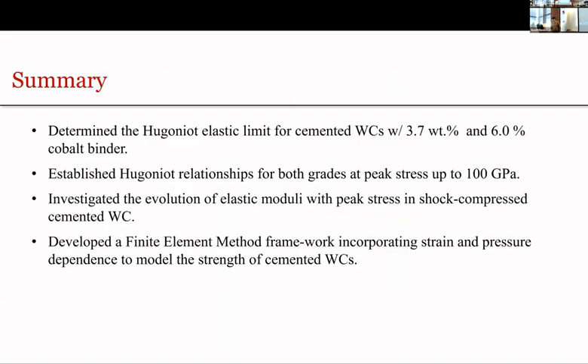So in summary, we have successfully determined the Hugoniot elastic limit for both grades and established the Hugoniot relationship for both grades as well. And also we investigated the evolution of the elastic moduli as a function of pressure. From the comparison with the theoretical value, we can have some insights into what the damage looks like inside a sample. And we developed this finite element method framework to capture the shock loading behavior. And that's all. Thank you.